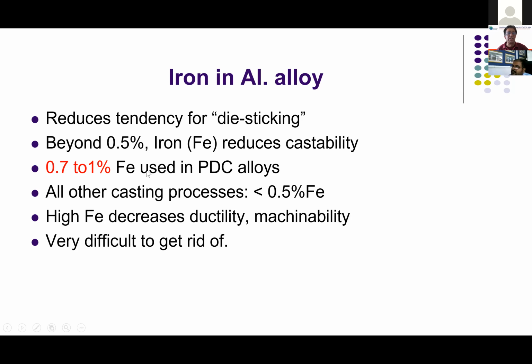There, what we do is that the normal practice is to maintain the iron around 1%, so that releasing is extremely good. But the problem is at 1% iron, your elongation is down to nothing. Casting becomes highly brittle. So the tendency to keep the iron at that percentage is no longer permissible. 5-6 years back, even 7 years back, they didn't mind 1% iron. But nowadays, no. We have to keep it 0.7 or even below.